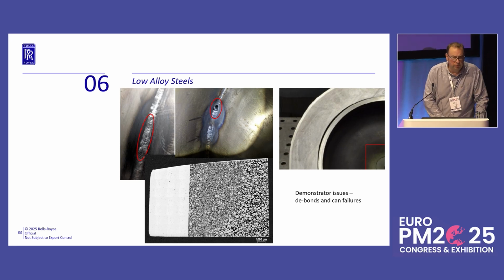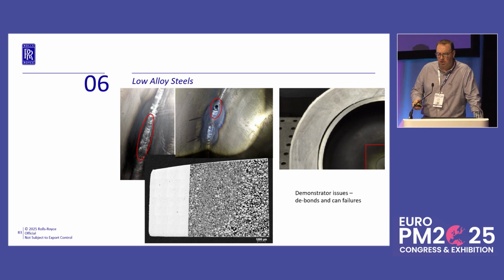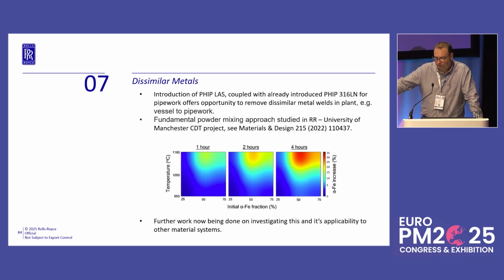So again, that's something that we might need to give some thought about, which is the most appropriate can material. Because if that happens earlier in the cycle, again, that could give us some quite considerable problems. So again, like other people, we've had the same thought. If I can make pretty much all of my other components out of powder, and I can now make my vessels out of powder, that opens up an opportunity to get rid of dissimilar metal welds, which are one of the banes in the nuclear industry.